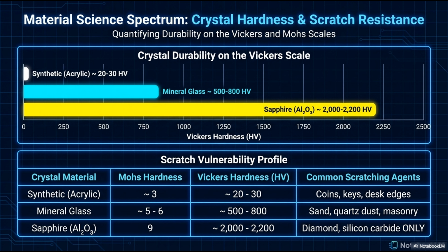Synthetic acrylic sits at a pathetic 20 to 30 HV. It is incredibly soft. Mineral glass represents a massive leap, sitting between 500 and 800 HV. It is respectable for daily wear. But look at the yellow bar for sapphire. It registers an astonishing 2000 to 2200 HV. Now, translate those numbers into the scratch vulnerability profile at the bottom.